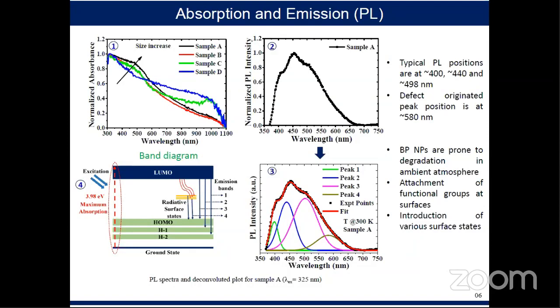In figure 2, I have represented the photoluminescence spectra with a 325 nanometer laser excitation. Three clear peaks are observable at approximately 400, 440, and 500 nanometers. But if you look closely, there is another higher wavelength contribution. Upon deconvolution in figure 3, we found another higher wavelength component at around 580 nanometers. The origin of these peaks can be explained using the band diagram in figure 4, where the radiative surface states contribute to this higher wavelength emission.